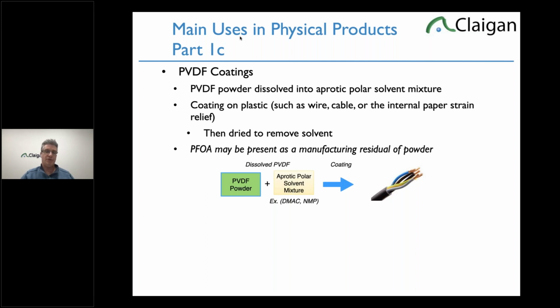The PFOA, if it was there, is restricted. But it doesn't have to be. There's lots of other choices. The 6,2-fluorotelomer sulfonate being the most common manufacturing aid, or its family, for making this situation. Again, it's powder, dissolved into a solvent. It's actually a solvent mixture. It's kind of a little more complicated than that, and then coated like a paint, and then dried, and that's the PVDF coating. We see it in wire and cable all the time to reduce friction.